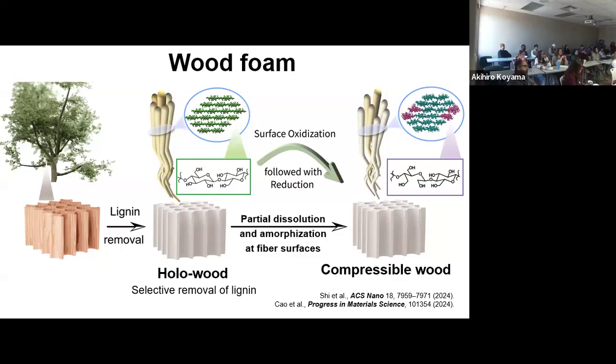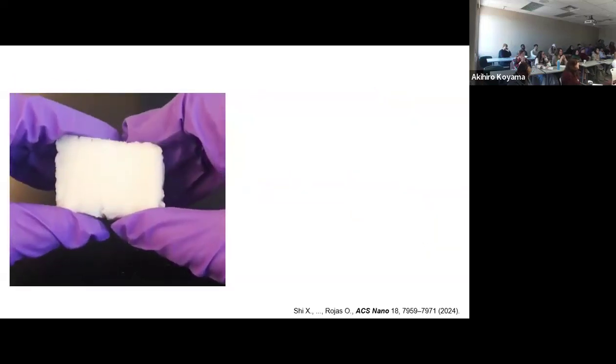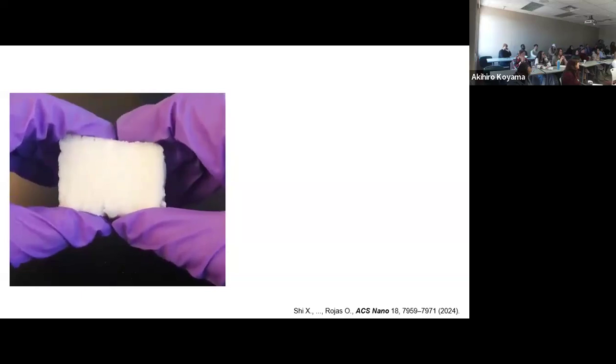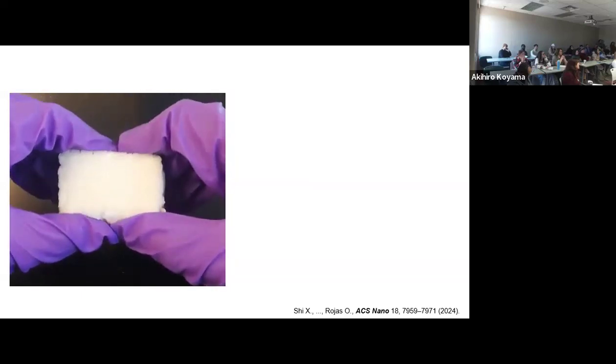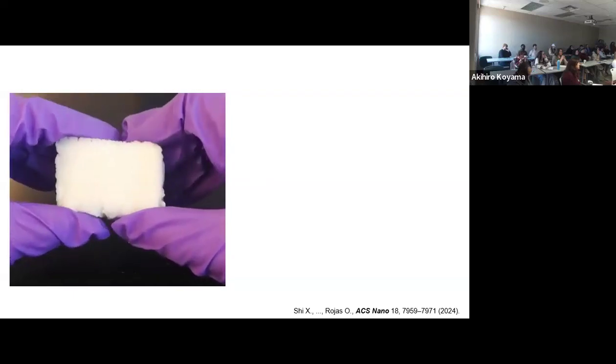Here we have then, after removal of lignin, the oxidation that I mentioned into aldehyde form, and then we follow with a reduction to make the aldehyde groups be converted into alcohol groups. So to neutralize, to make the material less reactive. So the densification that we showed before is not going to happen here, just the opposite. We transform the aldehyde groups into OH groups by reduction. The material then is no longer reactive, doesn't cross-link. It will lose mechanical strength, but it will gain in resiliency, because what you get at the end is a piece of wood that acts, looks, and behaves like a foam. And that's what you're seeing here. So it's a piece of wood that is a foam. It's not built from bottom.